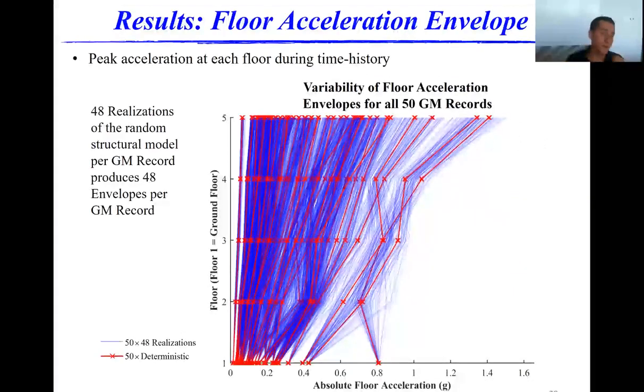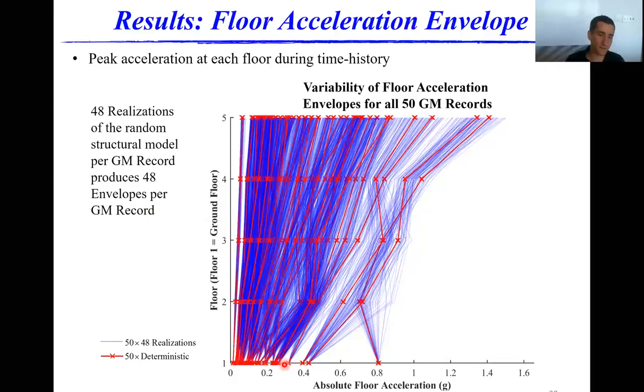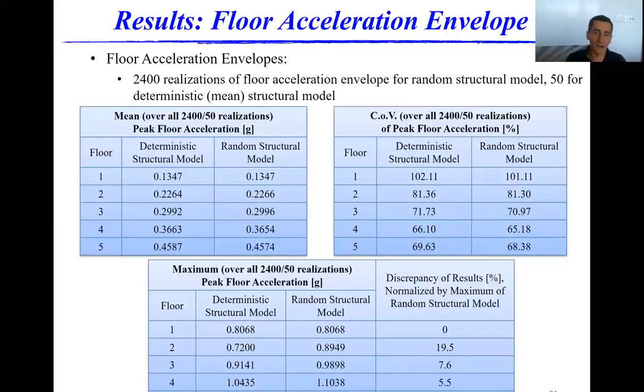And we can also look at all 2,400 envelopes at once and compare them to the 50 deterministic envelopes. And what we can see from here is that the scatter is relatively similar between the two. There are many more blue curves than the red curves, but they still cover the same broad range of accelerations along every story. So since they span such a broad range, several of the statistics that I measured for these EDPs are relatively identical between the deterministic and the random structural model. For example, the mean over all 2,400 random cases and the mean over 50 deterministic cases gets roughly the same number on each floor. Likewise, the coefficient of variation does not change much between the deterministic and the random structural model.